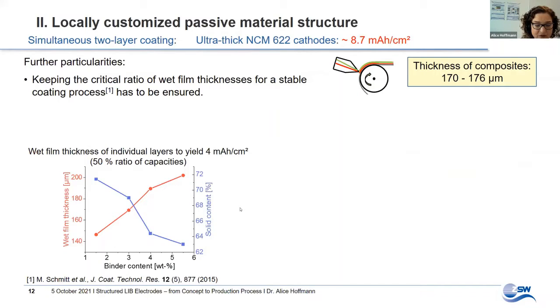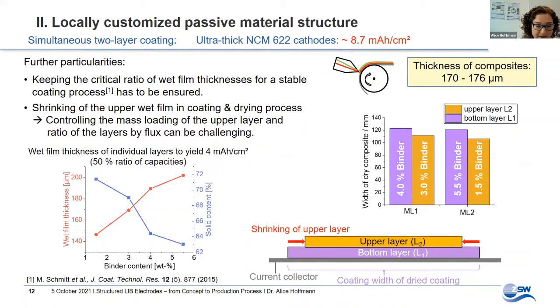The simultaneous two-layer slot die coating also entails further particularities. For a stable coating process avoiding air entrainment, a critical ratio of wet film thicknesses has to be kept. And this restricts the range of possible variations and has to be considered. As a further effect, when the suspensions are applied with their customized wet film thicknesses, the real layer thickness may not come out as intended.